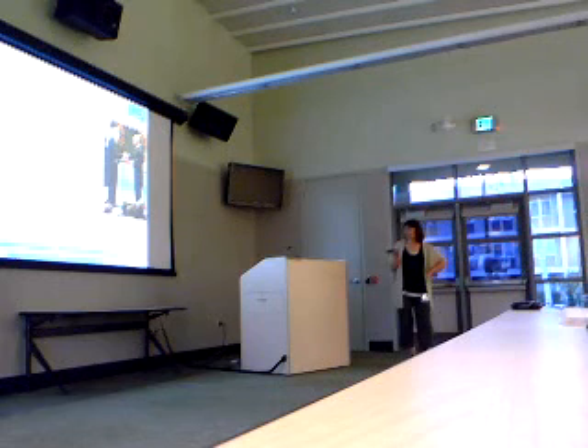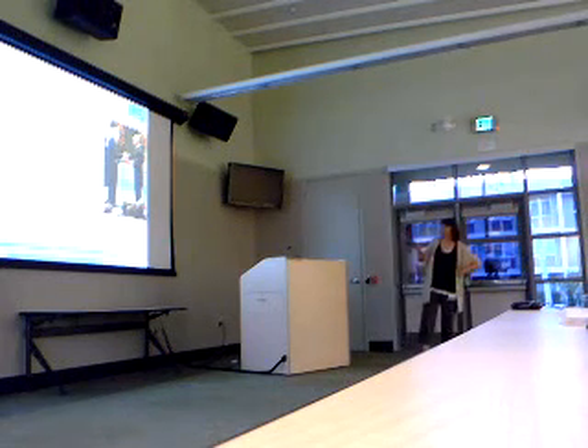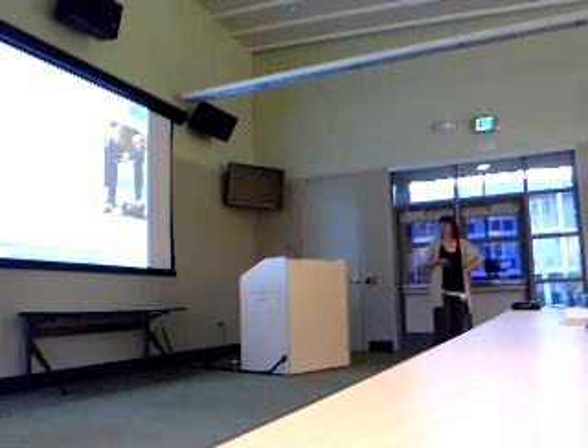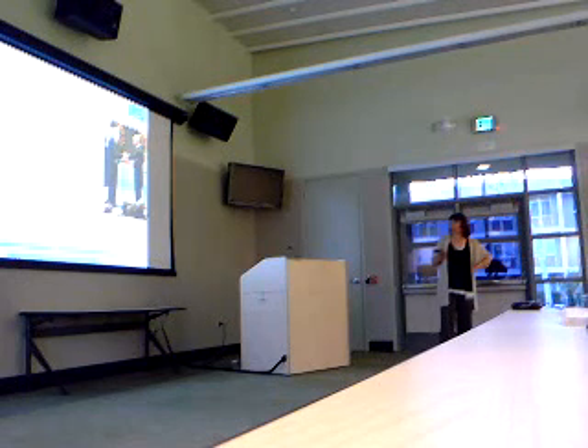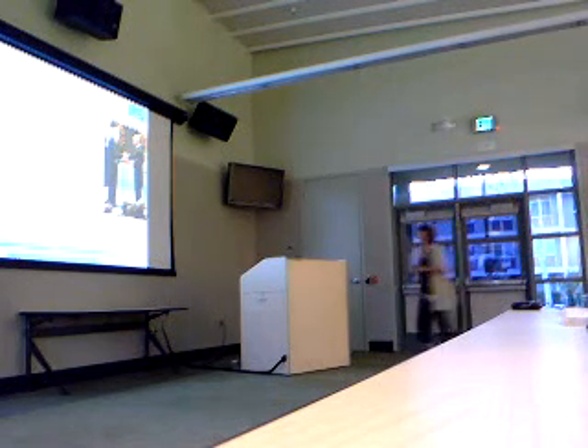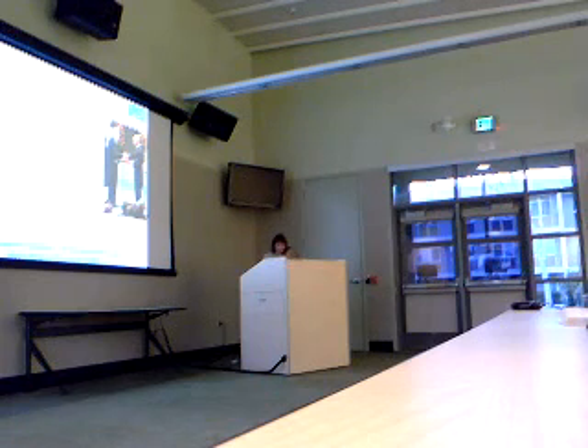And so we need to use some kind of extension, some kind of beyond-LDA method, and occasionally some kind of beyond-DFT method, like dynamical mean field. I think that all the results I'm going to show you tonight have been obtained with the LDA plus U method. I'll try and remember to point out if I show you any others. So remember that, depending on what kind of material you want to make, you have to be somewhat careful with the kind of density functional theory that you need to do. And that's all I wanted to say about the technique side.